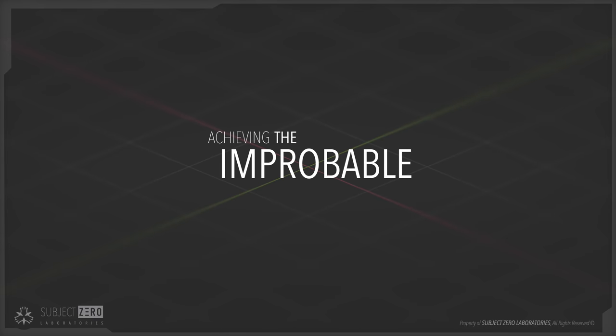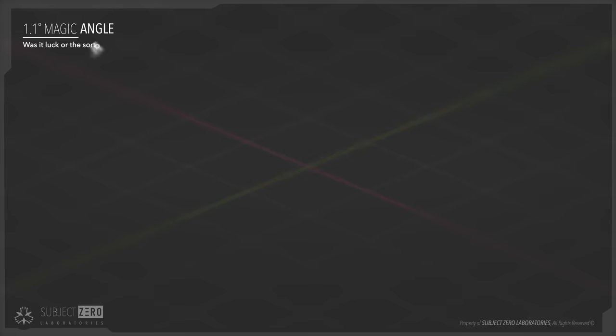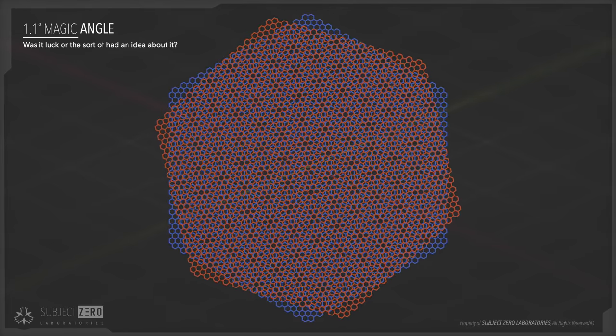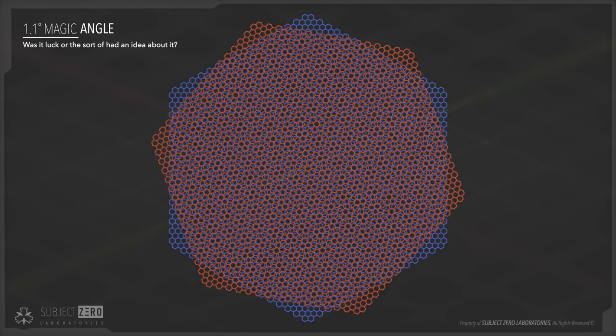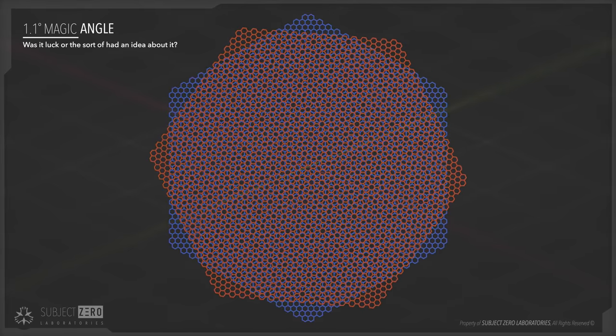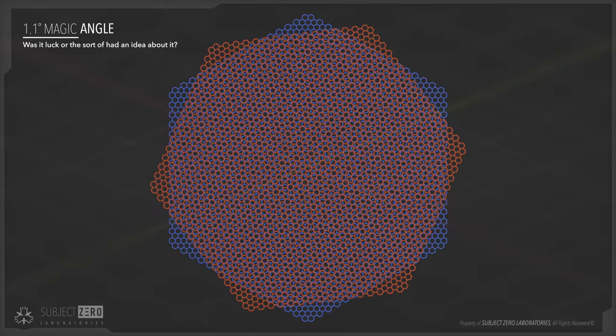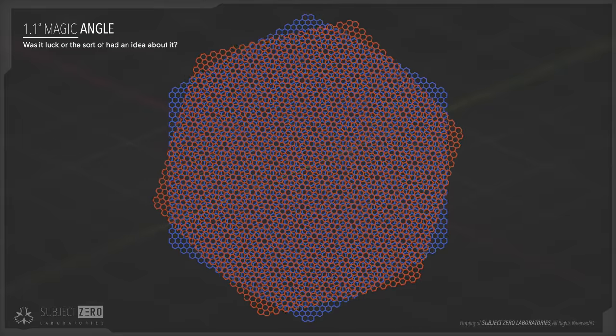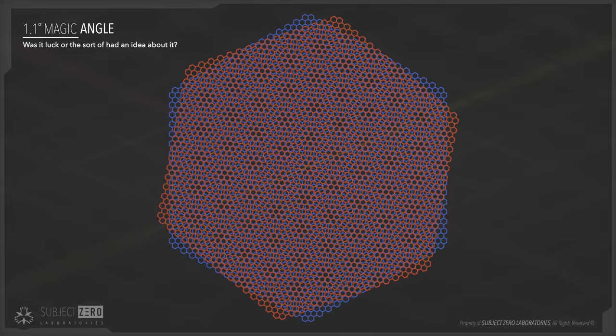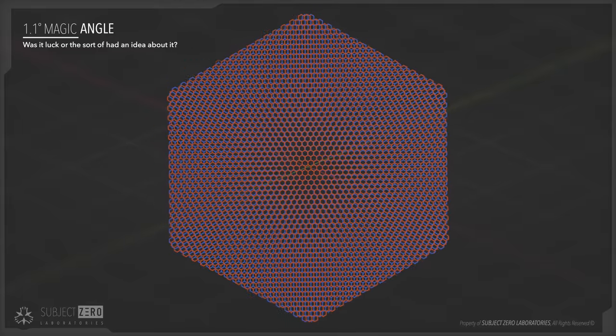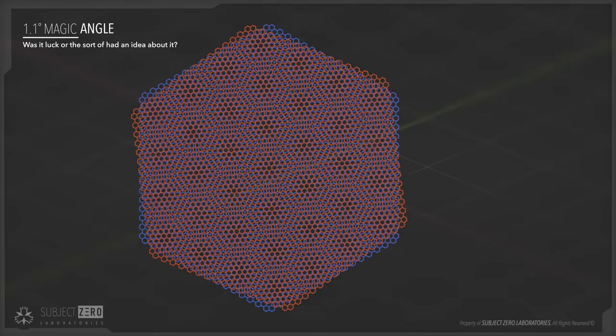Nevertheless, in 2018, scientists may have found the answer, and all they needed to do was put two graphene sheets on top of each other and rotate one of them at exactly 1.1 degrees. And I mean exactly here, cause if you move a little more, just like 0.1 degree, the opposite effect is seen. But how did they even get to this?